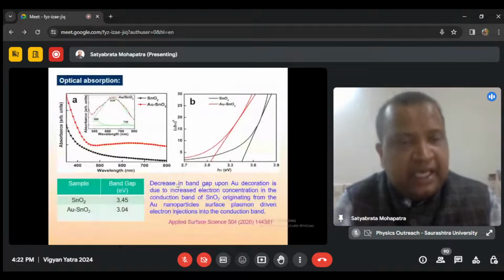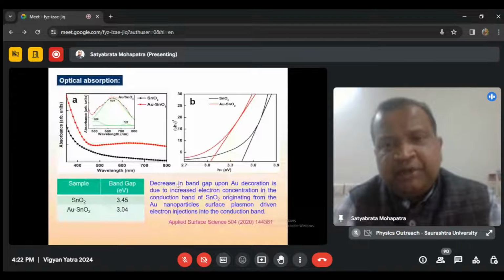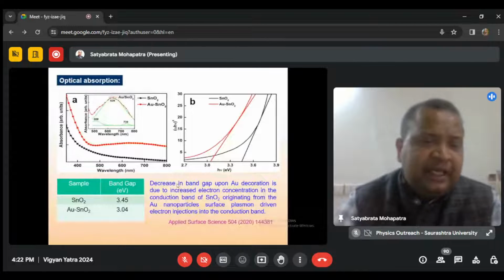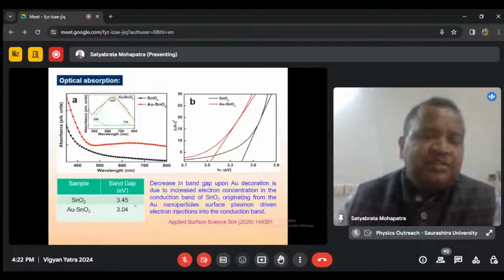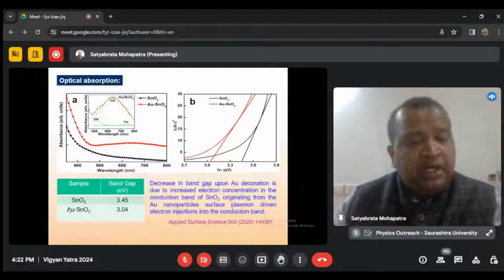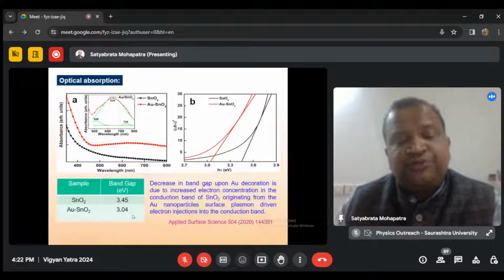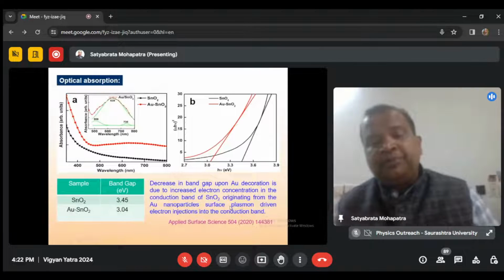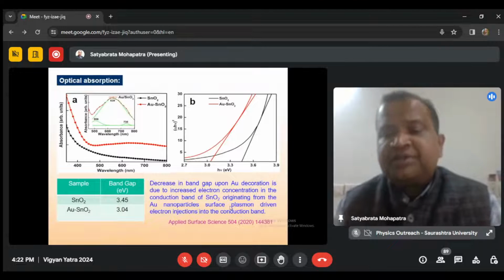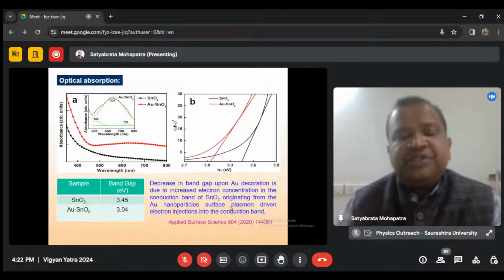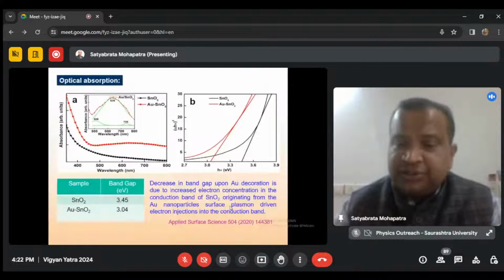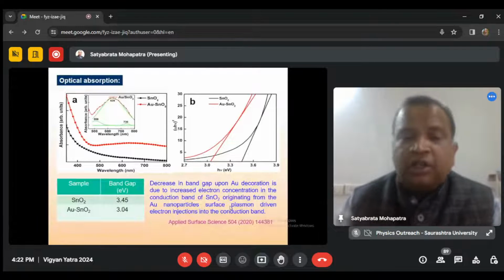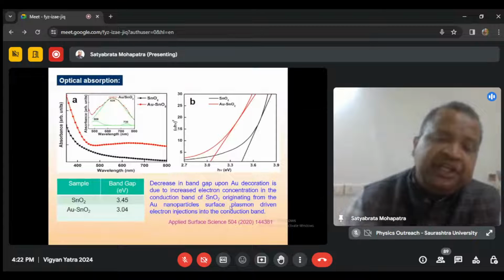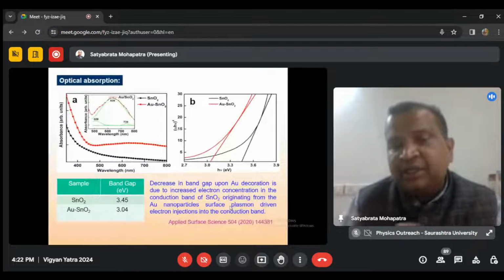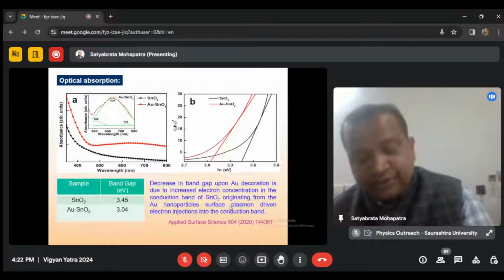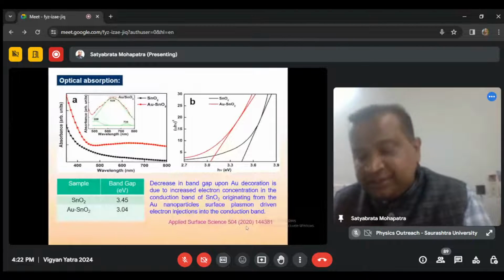Now, the optical absorption data shows that we estimated the band gap from this analysis. In the case of pure tin oxide it is 3.45 electron volt, and upon gold nanoparticle decoration it is reduced to 3.04 electron volt. This decrease in band gap on gold nanoparticle decoration is because of the increased electron concentration in the conduction band of tin oxide, which originates from surface plasmon-driven electron injection into the conduction band. So it depends on the plasmonic nanostructures, how many electrons you inject into the conduction band, and this is mainly responsible for the band gap reduction. This work was published in Applied Surface Science 3 years back.